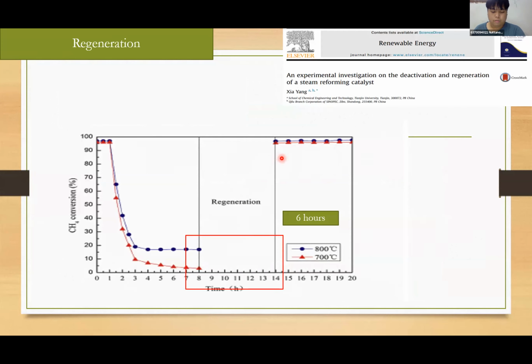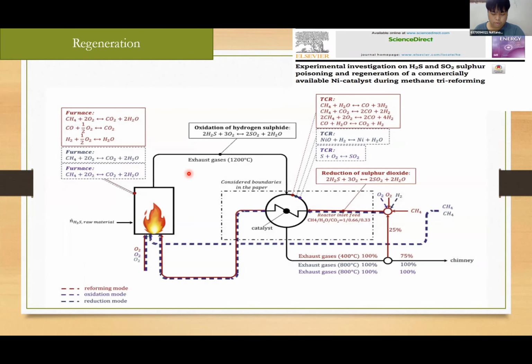Another paper was shown to confirm about sulfur poisoning and steam treatment. The results show that sulfur can easily adsorb on the nickel catalyst at low temperature, and the regeneration results show that it spent 6 hours in regeneration. To improve the performance of production and reduce the regeneration time, this paper will apply the thermal recuperation process of exhaust gas, and the steam treatment was replaced by oxygen treatment.